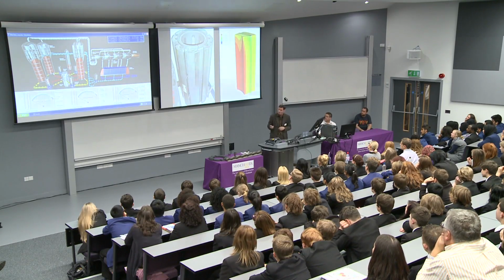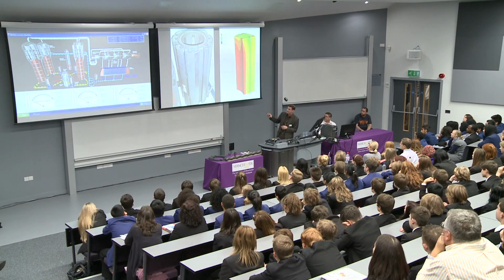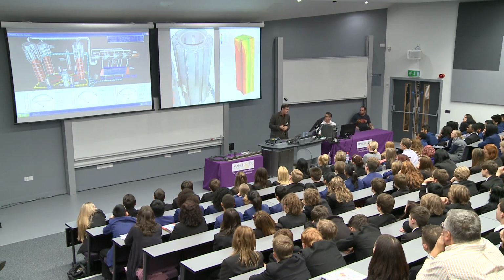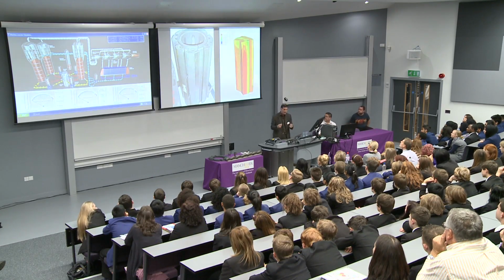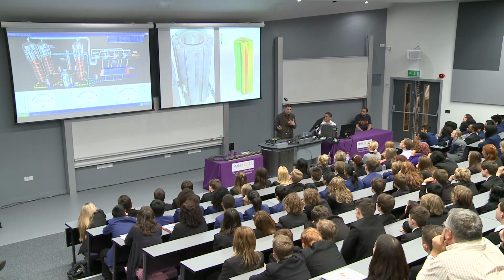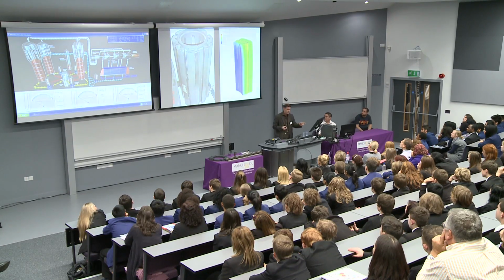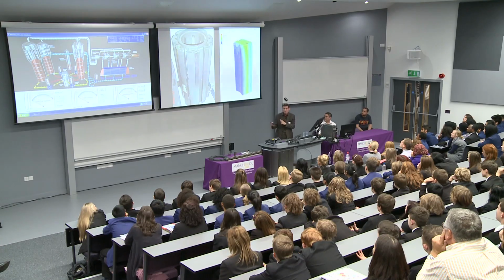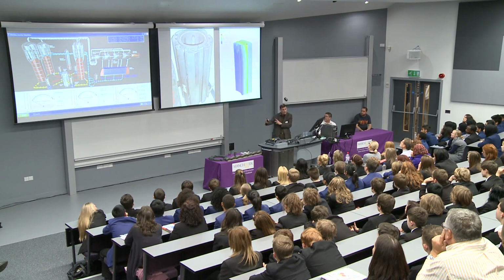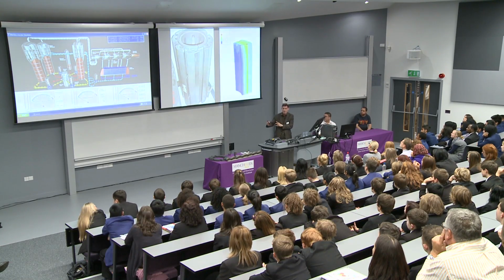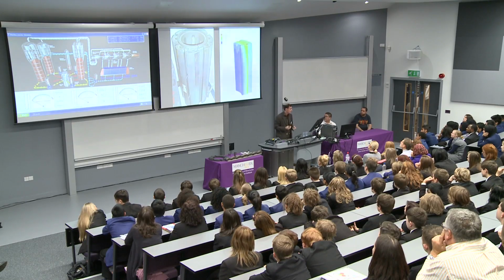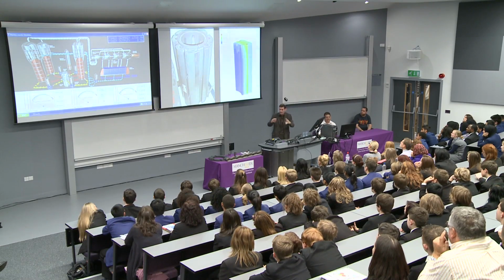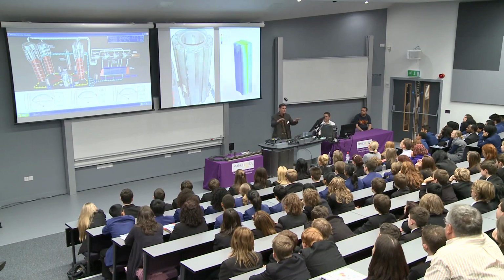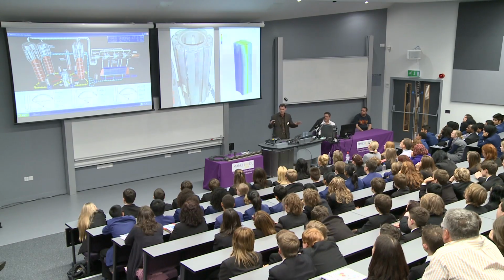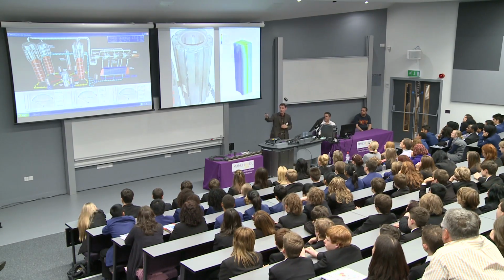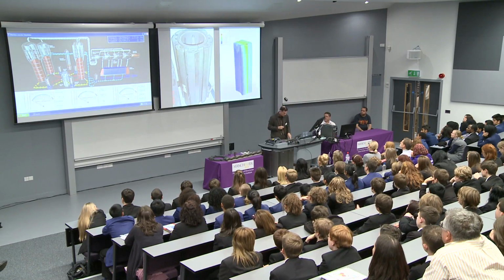So you can see on the left the brick. Here we've modeled a section of the brick. And you can see the red is where the stress is high and tensile. And blue, you'll see, is where it's compressive. And what you've seen there is that the stress changes through the graphite brick during its lifetime. And all of that information helps us to understand and predict how the core of an advanced gas-cooled reactor will behave during time. And we can predict that out into the future.